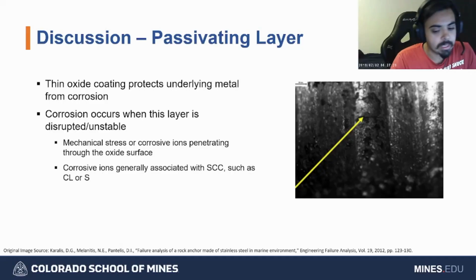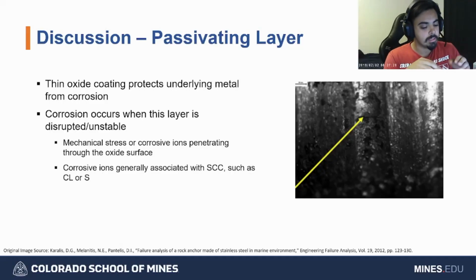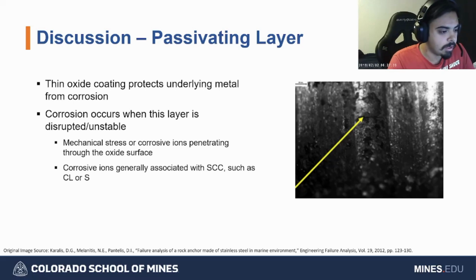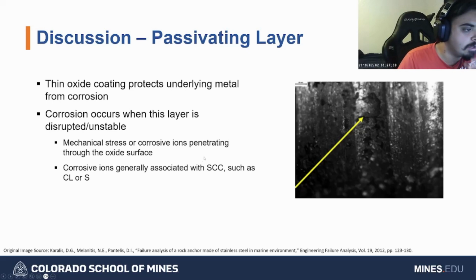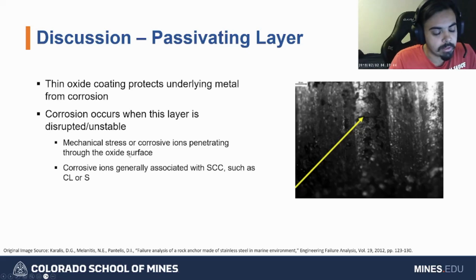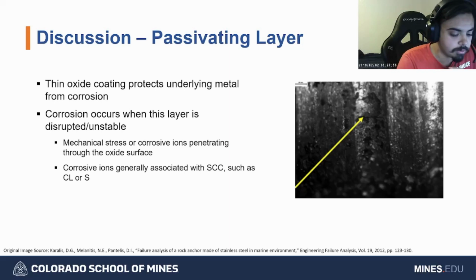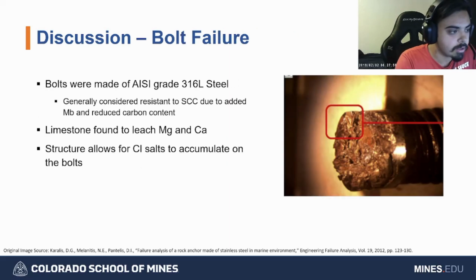Alright, first we'll discuss the passivating layer. Essentially, it is just a thin layer of oxide around the surface of steel, and what this does is protect the base metal from interacting with the environment, so corrosion or other things that want to interact with that steel. This is what prevents it. When this layer is disrupted or unstable for mechanical reasons, or if any of the corrosive ions diffuse through, you get corrosion. Corrosive ions with SCC generally diffuse straight through the surface, like chlorine or sulfur, so that's where you get this internal corrosion that causes the cracking.